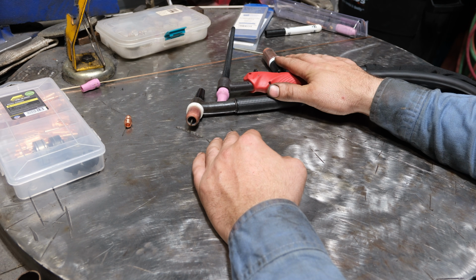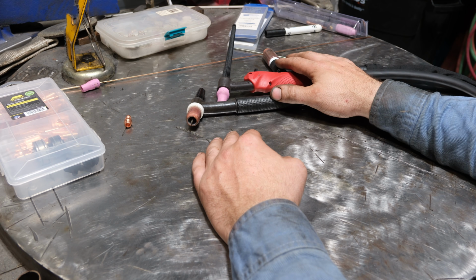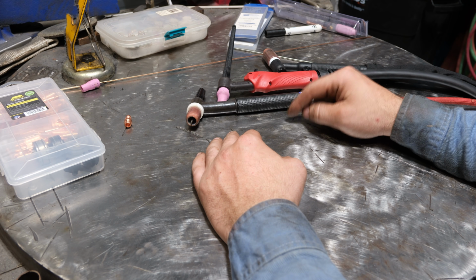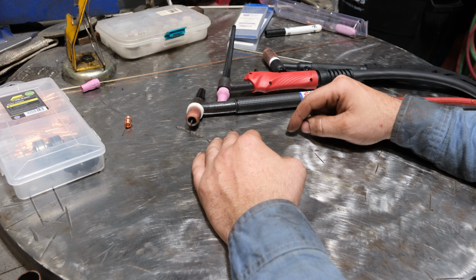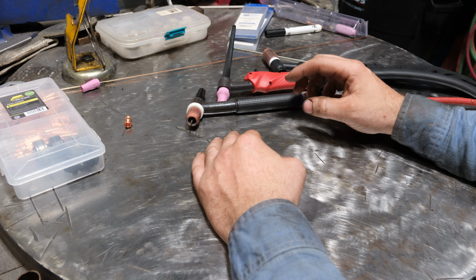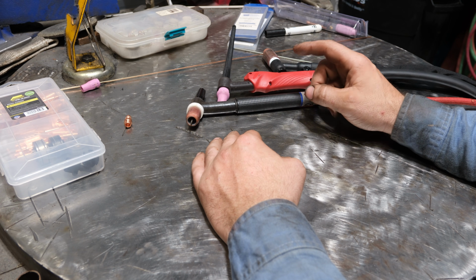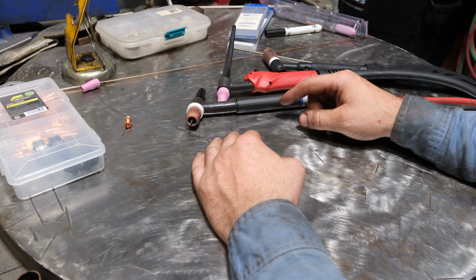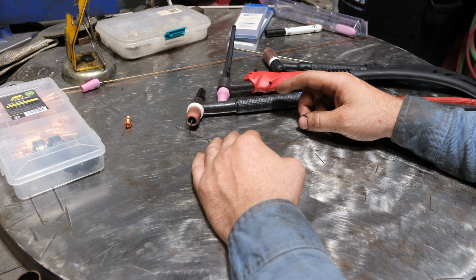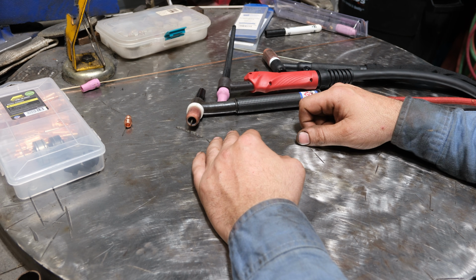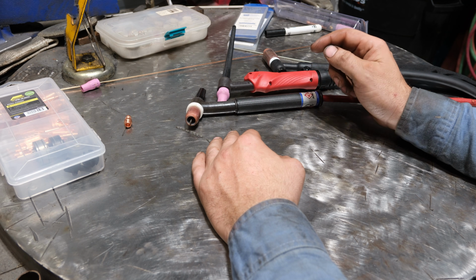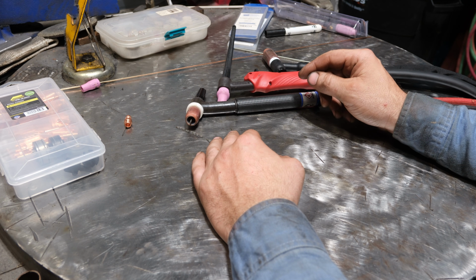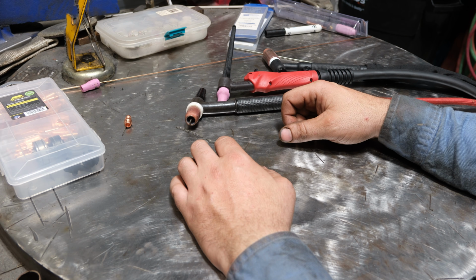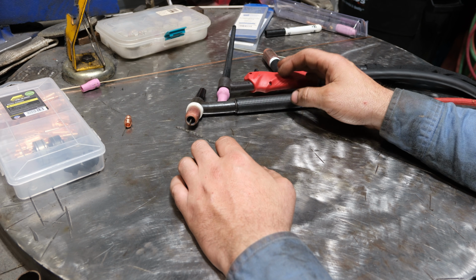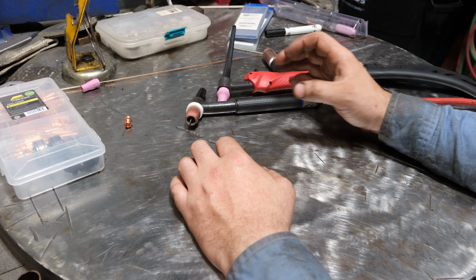And one of the great benefits with TIG welding over any of the other welding processes is that if you can weld steel in the flat position, you can weld it vertical up and you can weld it overhead easy. When you deal with stick and MIG, anyone who knows how to do those knows that vertical up welding is far more difficult than horizontal, and overhead welding is more difficult than flat or horizontal. And that is one of the great benefits with TIG because of how it functions in your molten pool. It's far easier, other than finding hand position, to weld vertical up than the other processes. So once you master flat position welds, it progresses very fast to out of position welds.